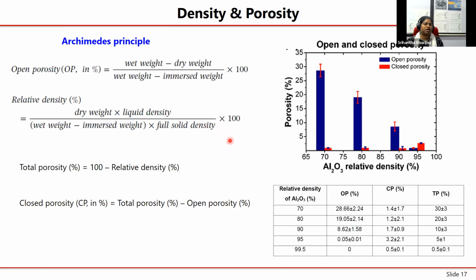So now we needed to quantify the density and porosity. It is porosity here, it is not simply just one value. Here we have to understand that the material can have open porosity as well as closed porosity. Thereby, we will use Archimedes principle, but in a slightly different manner. So what we can do is weigh the samples in the air, that is your so-called dry weight, and you can submerge your sample in the liquid. Let all the liquid penetrate into the open porosity of the sample. That's called the immersed weight.